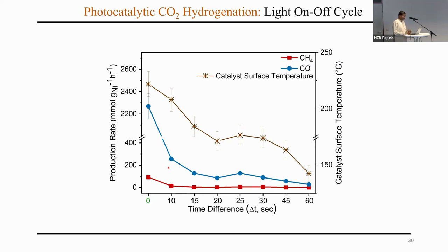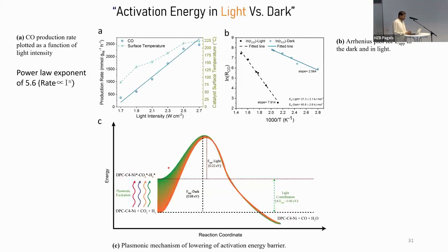To strengthen this argument, we tried to carry out a range of other experiments. One of these is the power law exponent. What it says is, if it is really a reaction because of the hot electron, so if I add more photons onto the black gold, I will generate more hot electrons. And if it is really the hot electron mediated reaction, then the reaction kinetics will increase, the production rate should also increase in a similar way. And that's what we see here.